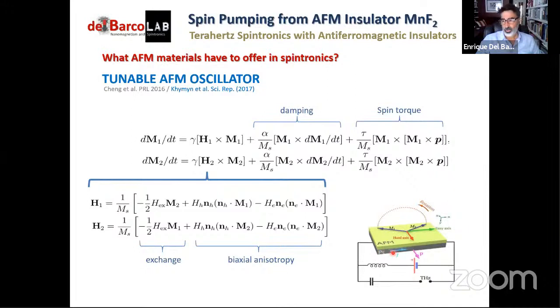So the principle of operation here is, now we have charge current flowing through platinum. The spin Hall effect is going to inject spin current perpendicular to the interface into the antiferromagnet. And with the polarization direction parallel to the interface and parallel to the hard axis, that is going to tilt the sublattice magnetizations out of the easy axis that is in the plane. And the exchange field is going to make this oscillate in a plane that is perpendicular to the interface between the two materials. That oscillation is going to generate an oscillating electric field that is going to radiate terahertz radiation out into space.